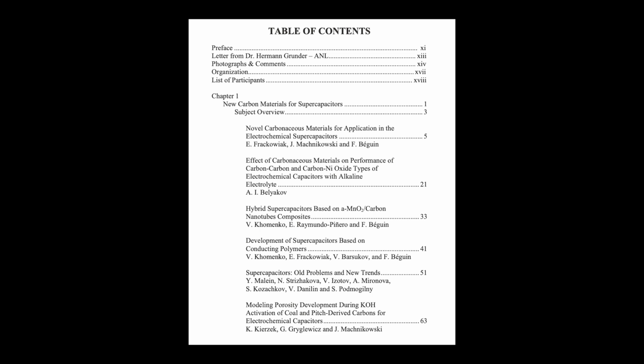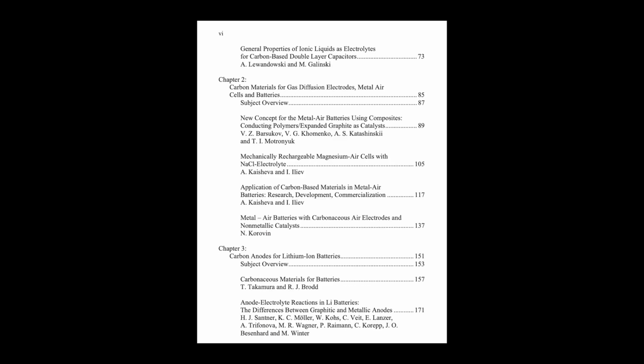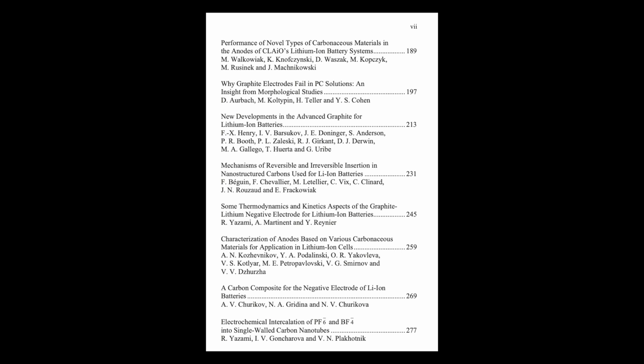Okay, we have definitely gone deep today, really unpacking this research collection almost chapter by chapter like we planned. It really gives you a sense of the breadth and depth of work just on carbon materials for energy storage. It's everywhere, doing different jobs. From supercaps needing that massive surface area, to metal air needing robust, gas-permeable, water-managing electrodes, and especially lithium-ion anodes, with all the complexity of the SEI, the intercalation, the volume changes. Carbon is the common thread, but the challenges and solutions are incredibly diverse depending on the application.